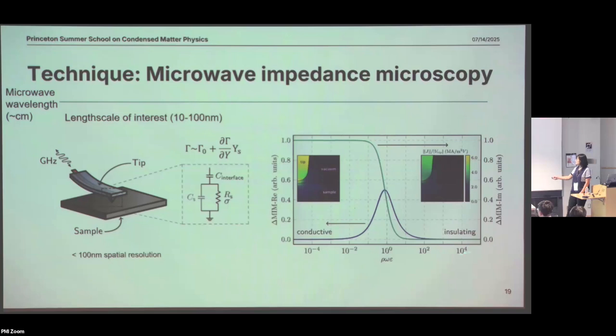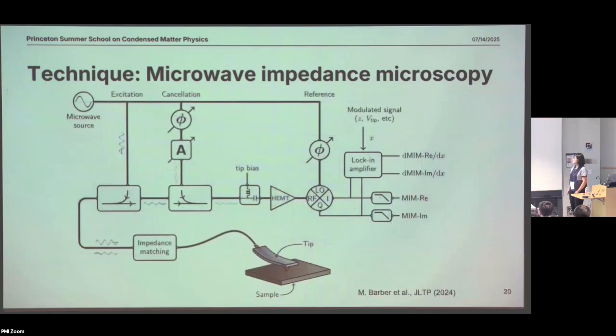And similarly for the real part, you also have a lot of sensitivity when you're at the intermediate conductivity regime. But then when you go to very insulating, like a perfect insulator, or a perfect metal, it becomes very small. So that's how we get some sensitivity to the local conductivity. And that is a way of doing those DC measurements.